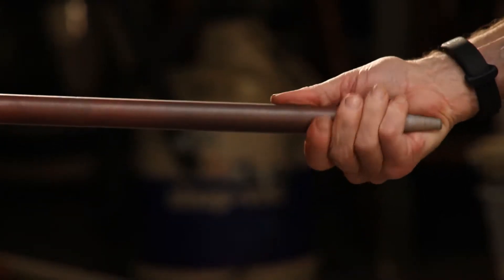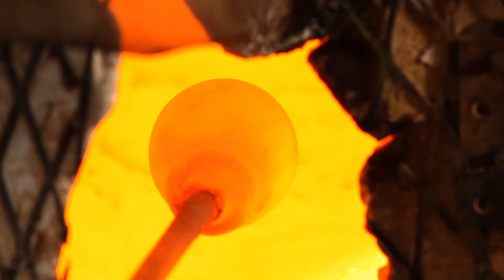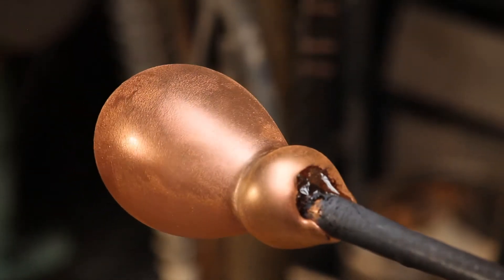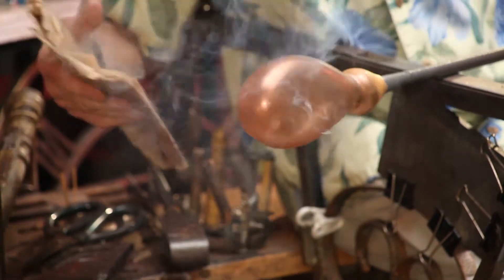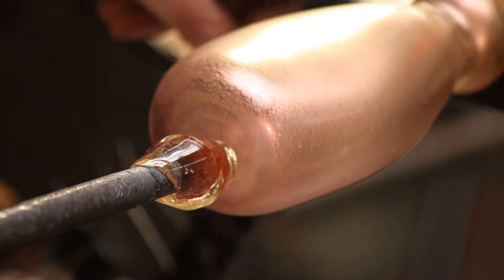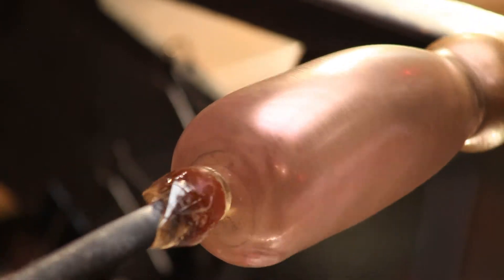A very hot punty will often work, especially if the piece is small or has been inflated some since being coated. It is also possible to torch a spot for the punty, though the reducing flame of the torch degrades the lustered surface and changes the powder's optical quality, making it a browner spot, which may not be desirable.